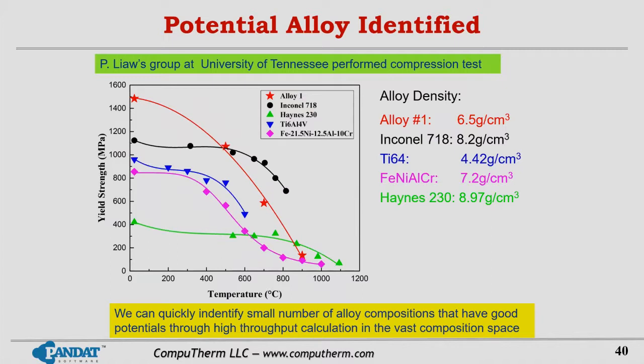For example, this shows one case. We compare the yield strength of this newly found high entropy alloy with 4 other alloys, some of which are commercial alloys. At low temperature, this alloy has the best yield strength, very high. But at high temperature, it is not as good as Inconel 718. However, this alloy has a much lower density than 718.